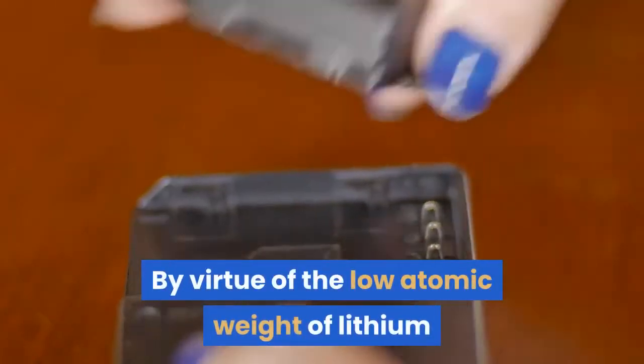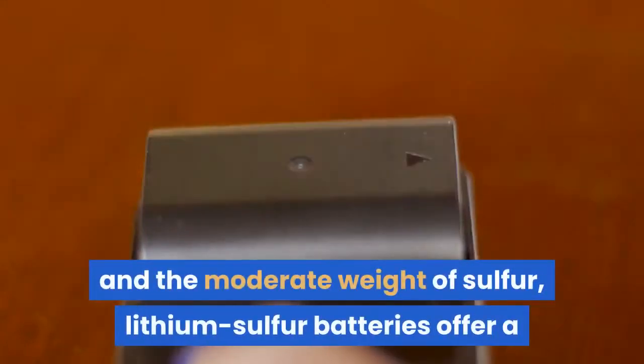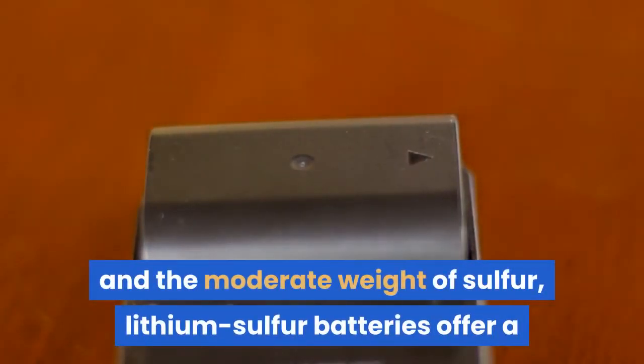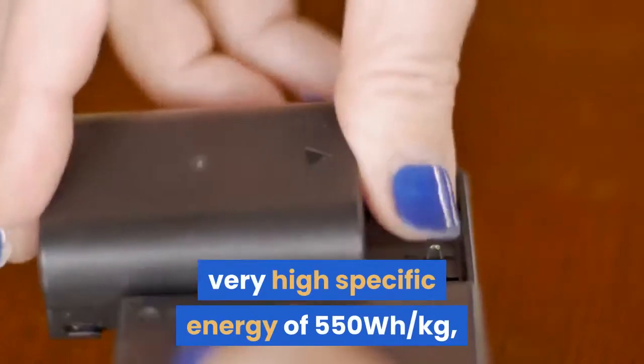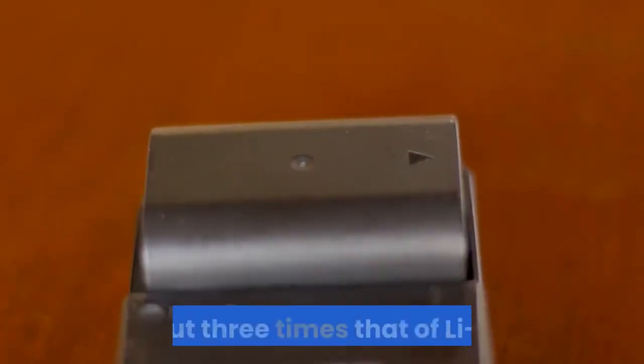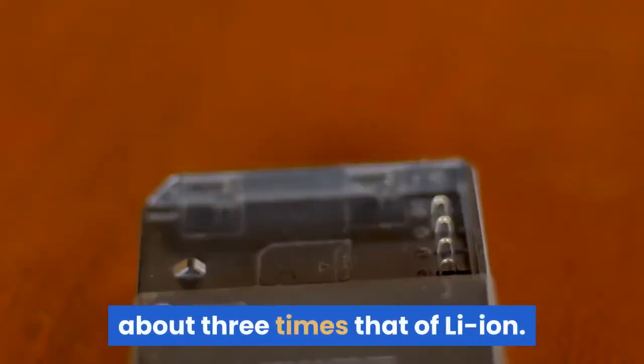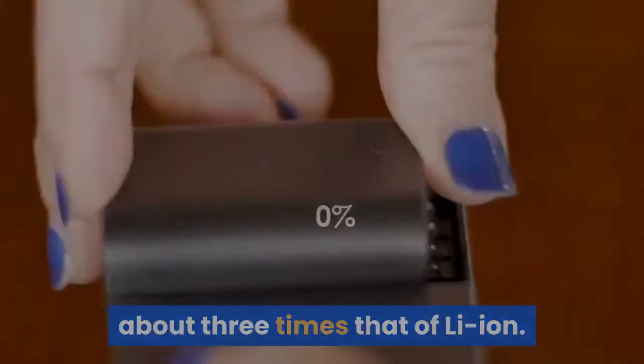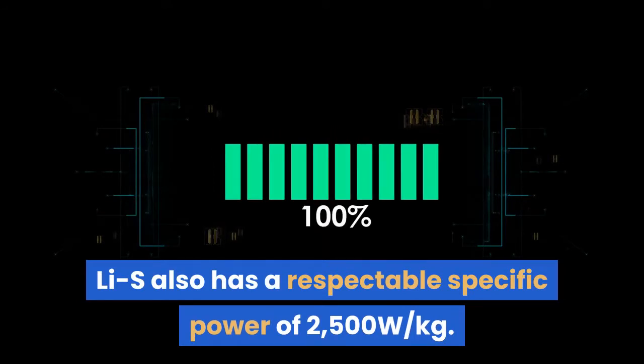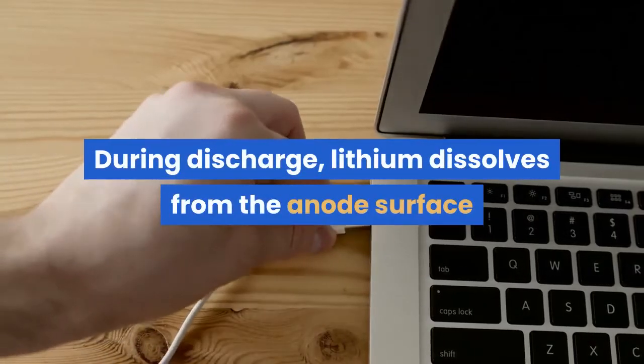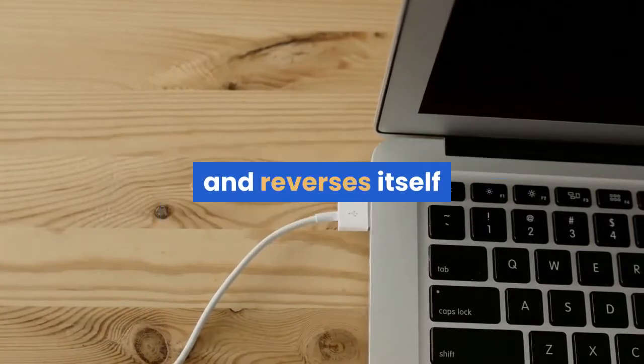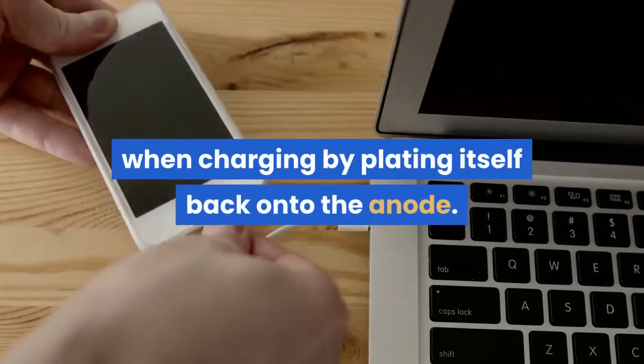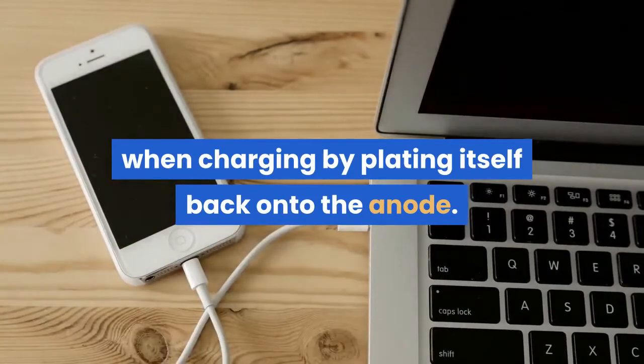Lithium-sulfur, Li-S. By virtue of the low atomic weight of lithium and the moderate weight of sulfur, lithium-sulfur batteries offer a very high specific energy of 550 watt-hours per kilogram, about 3 times that of Li-ion. Li-S also has a respectable specific power of 2,500 W/kg. During discharge, lithium dissolves from the anode surface and reverses itself when charging by plating itself back onto the anode.